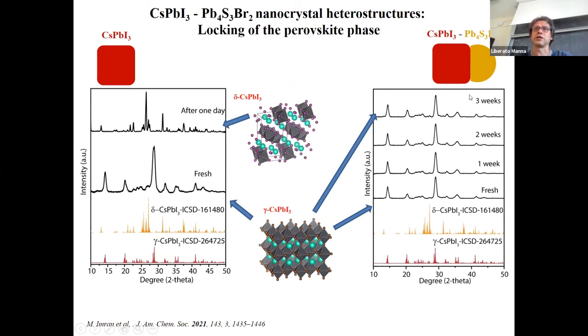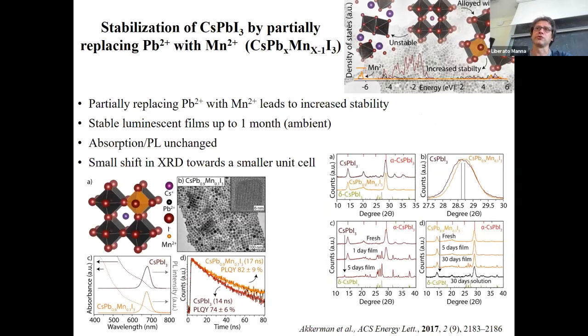Instead, when you make the heterostructure, because now there is a very nice epitaxial match between the perovskite and the chalco halide, the perovskite structure is locked in place, and it doesn't undergo any transition to the delta phase. So this can be used, for example, in photovoltaic devices, or in any other devices where you don't want this transition to occur. And now, just very quickly, you can prevent this transition from the perovskite phase to the non-perovskite phase also by other means.